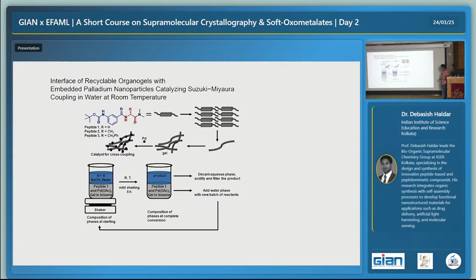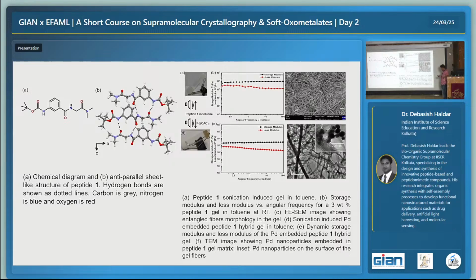After the reaction at room temperature with mild shaking for 5 hours, the product will form, and then we will just decant the aqueous layer from the top of the gel, and again we will fill up the aqueous layer with the reagents, and that cycle can be continued. So that is what we have planned.